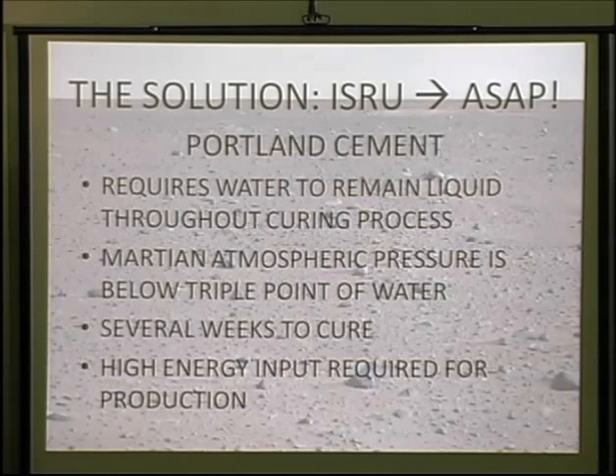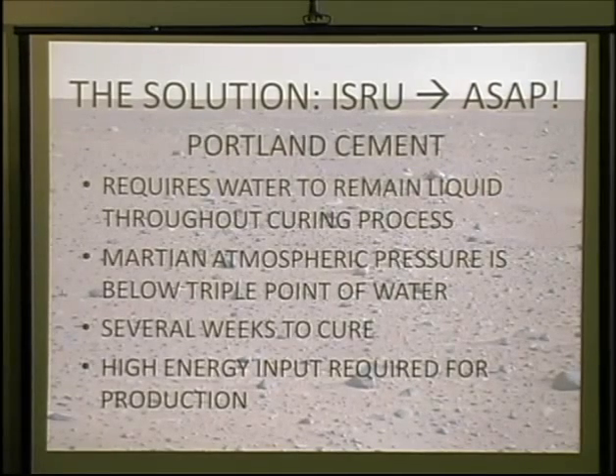The Portland cement we use here on Earth won't work on Mars for a lot of reasons. One is it requires water to remain liquid for a long time, several weeks. And in the Martian atmosphere, it'll evaporate very quickly, and it'll also boil, because the Martian atmosphere is almost always below the triple point of water. And it also takes a lot of energy to produce it at very high temperatures from the raw materials available.